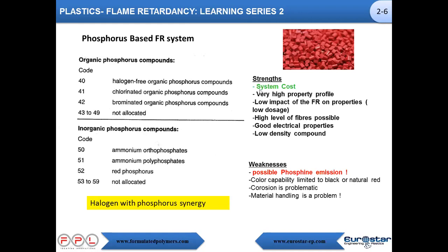You don't need so much to flame-retard plastics, below 10%. So the system cost is very interesting. The property profile is high, and the impact on the other properties is really low. You can go up to 50% glass fiber with this material. It still has very good electrical properties, and density is low. A possible concern is phosphine emission. I'd say it was very true in past years. Now, under the right processing conditions, it's not something you have to fear too much. It can be very well controlled.